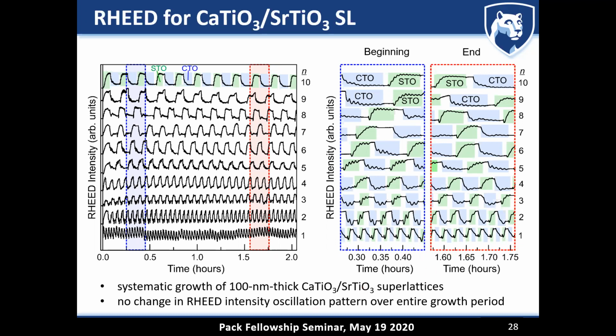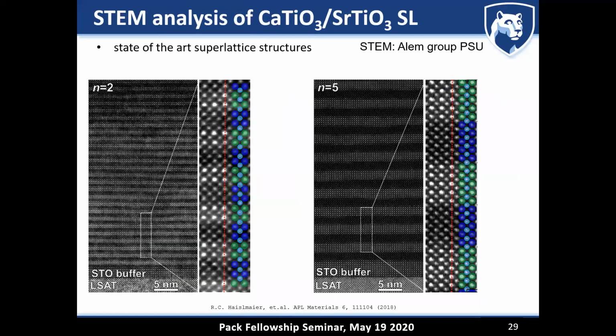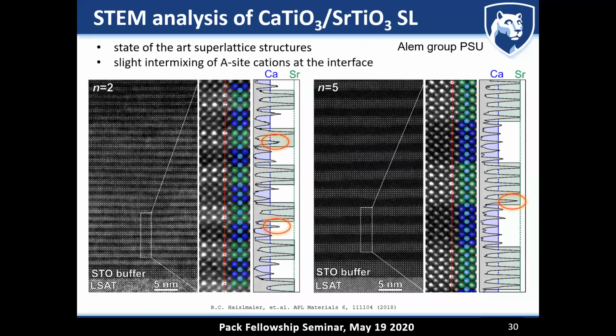Now, this is not, you know, a very direct look at how these superlattices look like. It would be much nicer to take a cross section and really have a look at it. And you can see that really films and superlattices grown by hybrid molecular beam epitaxy give rise to state-of-the-art superlattice structures.